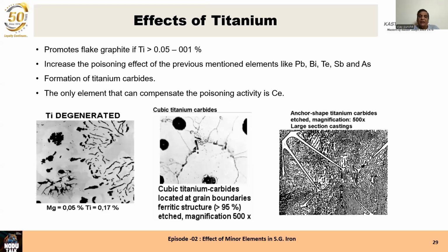It forms carbides, and the carbides cannot be seen at lower magnification. The only element that can neutralize this bad effect of titanium is cerium. Once again, a good enough reason to use rare earth containing ferrosilicon magnesium. In rare earths, cerium is present up to 40%. So that is good enough to take care of all these bad subversive elements which we are unable to detect, unable to determine, and unable to take any action on. So having cerium acts like a good neutralizer for all the subversive elements.